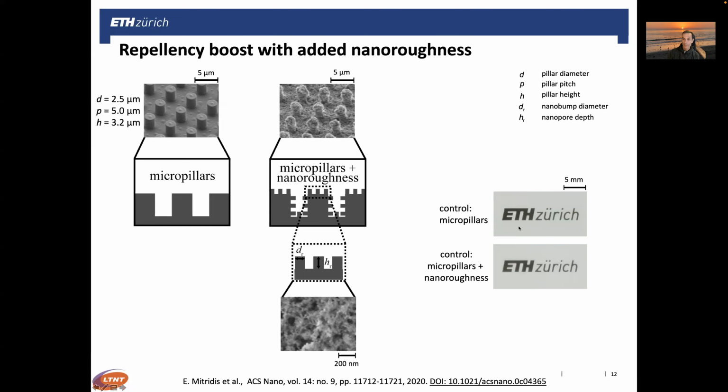We looked into the case where we have a micropillar surface, a superhydrophobic micropillar surface, and a micropillar surface with a nano roughness that goes on top of our metasurface effect. You see that the additional layer bringing the nano roughness does not affect very much the transparency.